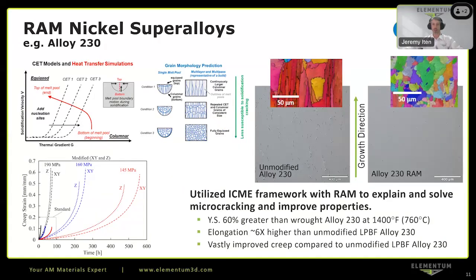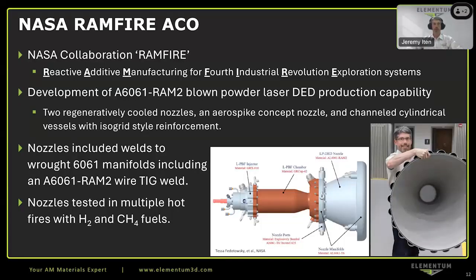The same process is also useful for other alloy systems, including nickel alloys. A Haynes 230 type alloy system is one that's also known to suffer from solidification cracking when printed by a laser powder bed fusion type process. Again, you get these hair-like cracks that you can see in that microstructure, and again, due to the columnar solidification texture that you get. With our RAM process, we've been able to eliminate that cracking, greatly improve the performance, and get much more reliable and improved properties from this. This work also involved integrated computational materials engineering together with the Colorado School of Mines and was supported by the Office of Naval Research.